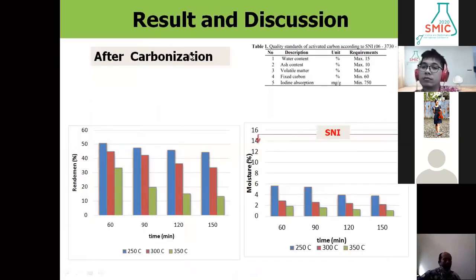This is the result. This is the sample, our fine carbon after carbonization. And this is the table containing the SNI standards for activated carbon. That is the rendement, and also carbonization time for the 60 minutes is very good enough. And I think it's good for us also because we do not need much time for performing carbonization. For moisture content, all the values here are below the required number of SNI. So it is enough, it is good because all of them are less than